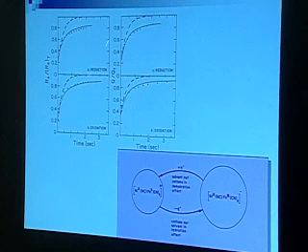And the point to make is, for all these curves, and I'll have to explain what these curves are later, it doesn't matter what you do. The curves are identical. So in other words, when we see current flowing, Faraday is right. Molecules get oxidized. So for every Coulomb we pass over here, we see 10 to the minus 5 moles of iron 2 oxidized to iron 3. So I can use either of these panels. Okay, so we're going to take a look at that.